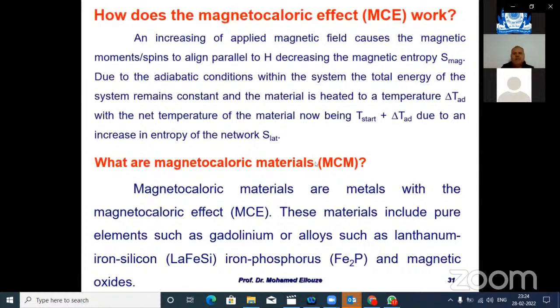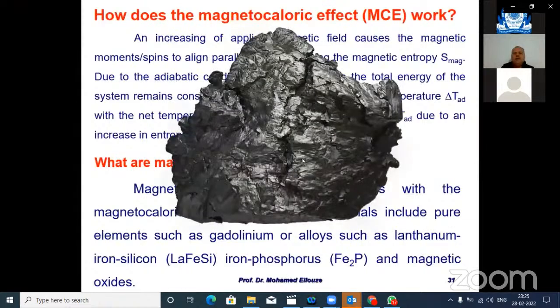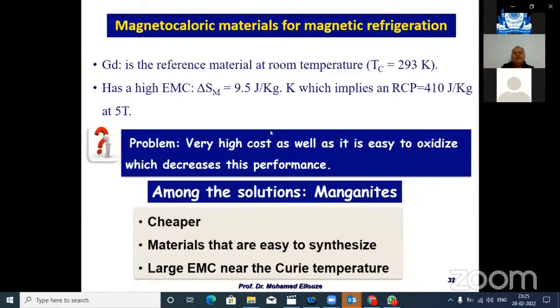What are the magnetocaloric materials? These include pure elements such as gadolinium, or alloys. This is a photo of natural gadolinium. This kind of natural gadolinium is the reference material at room temperature, and we have a variation of magnetic entropy of about 10 joules per kilogram per Kelvin, which gives a high RCP.